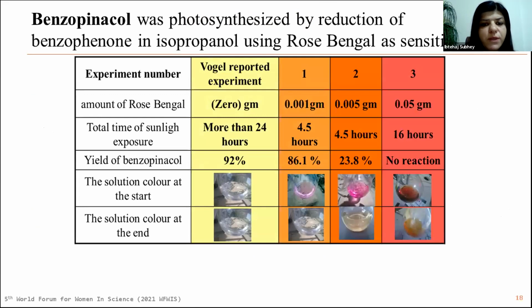This table shows 4 experiments for benzopinacol photosynthesis. In these experiments, we see Vogel-reported experiments. We used here benzophenone, isopropanol, and we used rose bengal as sensitizer. In this experiment, the amount of rose bengal, according to Vogel-reported experiments, is 0 gram. The time required for complete reaction is more than 24 hours in 92% yield.